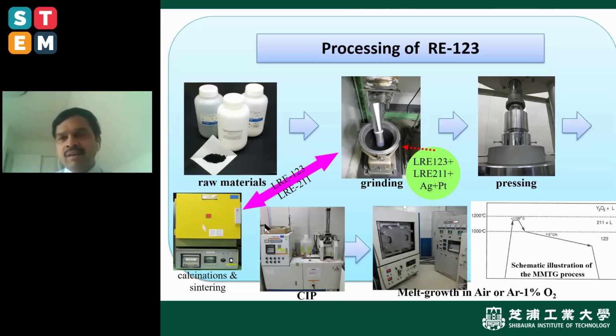You can see this is a very easy material that can be processed starting from the oxides. Then we mix them in the normal process, along with sintering and calcination. Finally we make the pellet and insert it into a furnace. The material is heated to more than 1000 degrees centigrade and cooled below 1000 degrees centigrade at 1 degree centigrade per hour.